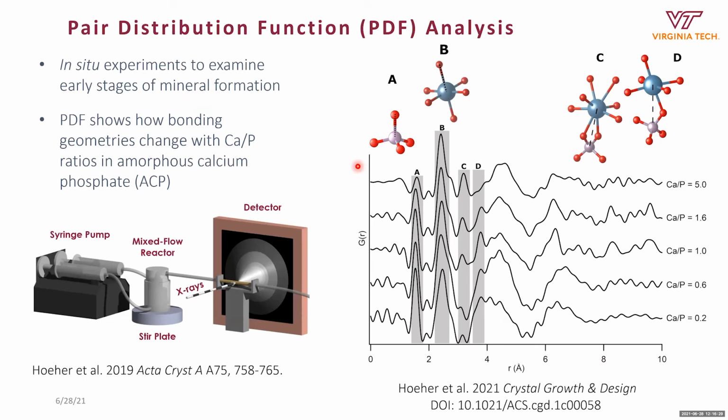And so we've been using this kind of approach for some in situ experiments to examine the early stages of mineral formation. This is an approach we've developed over the last couple of years that uses mixed flow reactors, where we're synthesizing materials inside the reactor, pumping in reagents using a syringe pump. We're then passing that solution as it's exiting the reactor with the newly formed particles through the X-ray beam, and we're using our detector to collect the diffraction data.